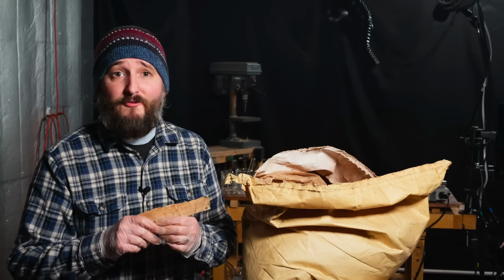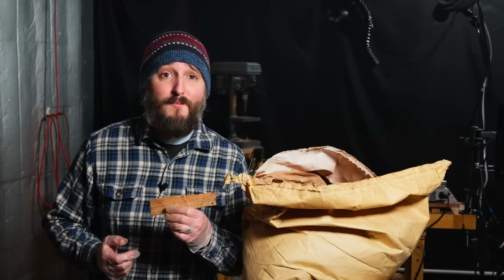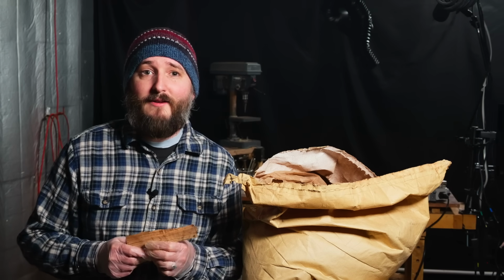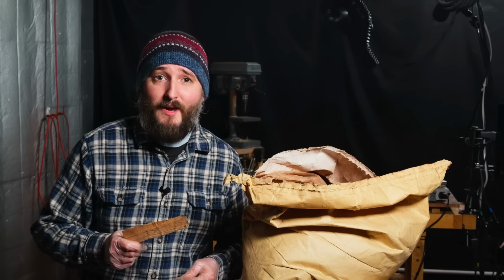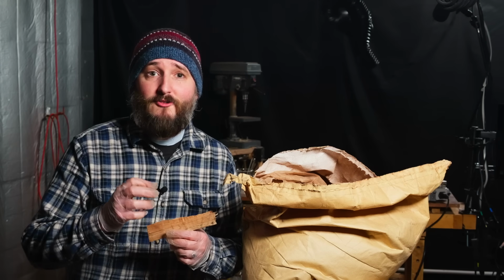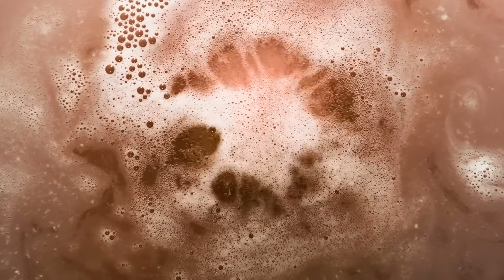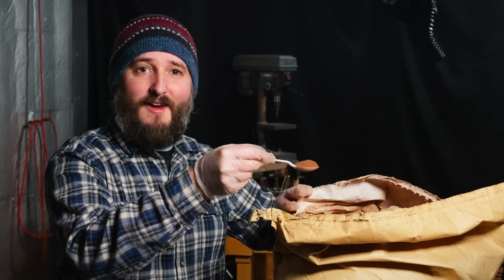To collect cellulose from wood, the lignin needs to be removed, and the way that that's done is to react it with highly charged sulfur compounds, which bind to the lignin, turning it into something like a detergent, which is soluble in water so that it can just be washed out to leave clean cellulose behind. This is the waste that's left over, sodium lignosulfonate.